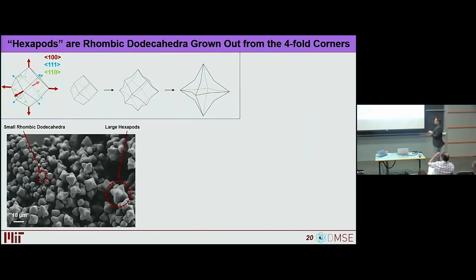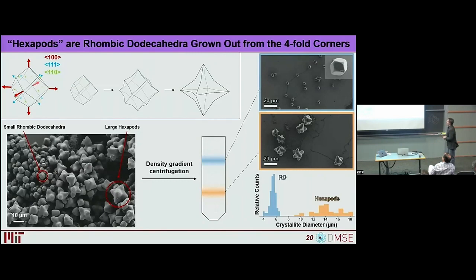Just by looking by eye, you can tend to see that smaller structures tend to be these rhombic dodecahedra, and these hexapods only form when they're larger. We can be a little bit more quantitative with that. If we do density gradient centrifugation to separate out these different crystallites by size, we can see that indeed the rhombic dodecahedra tend to be smaller, and the hexapods tend to be much larger. So what exactly is going on here?